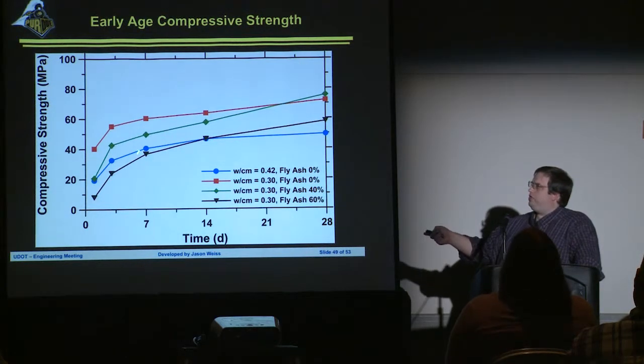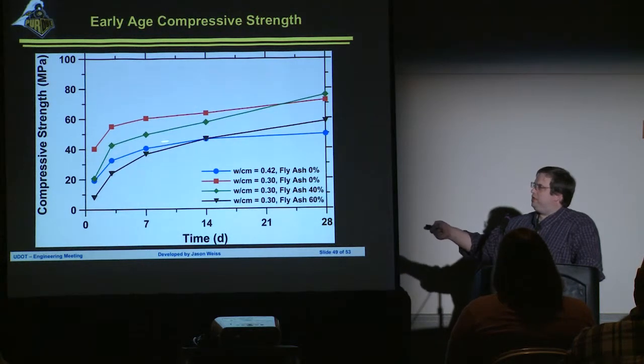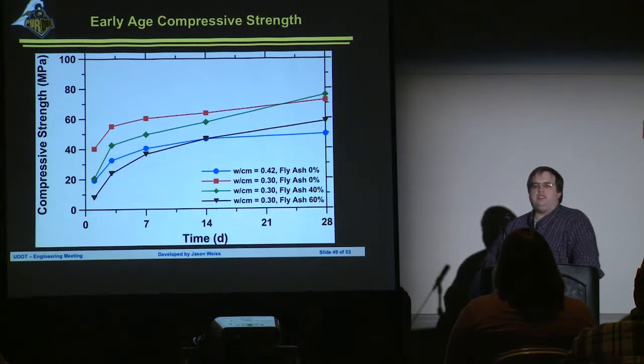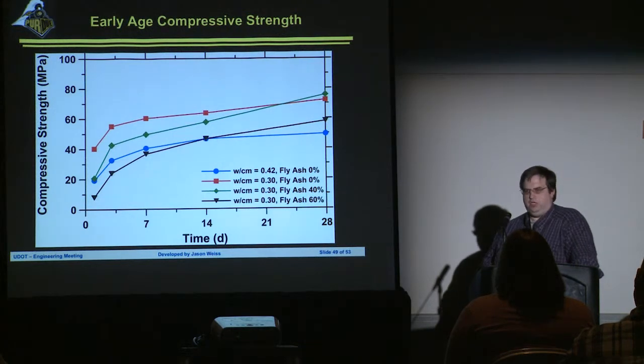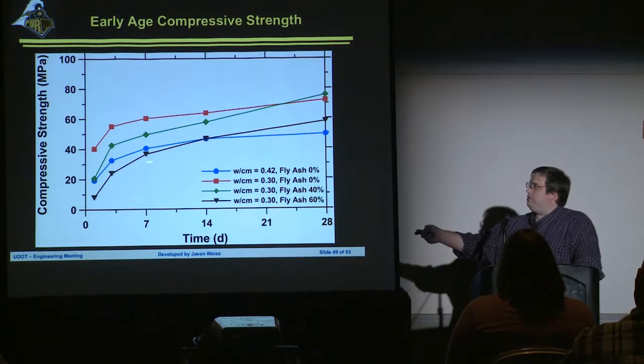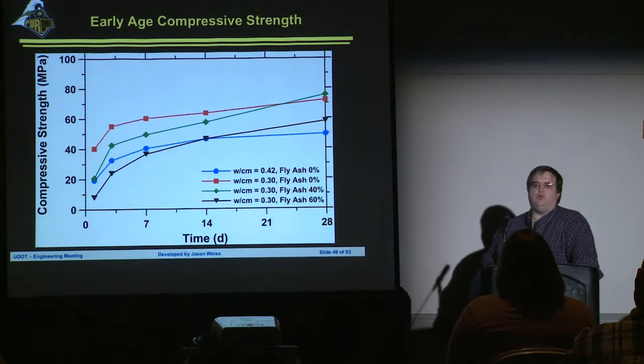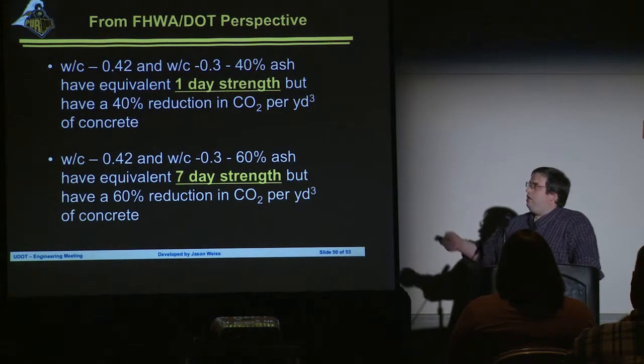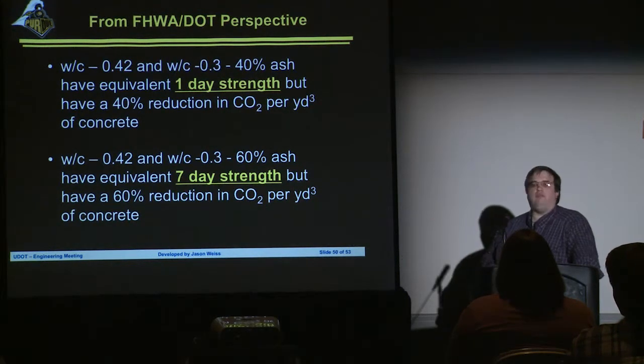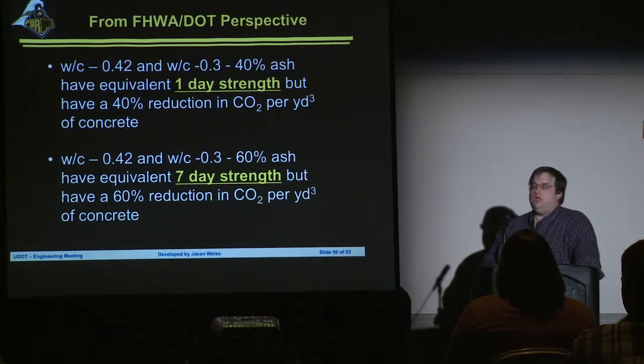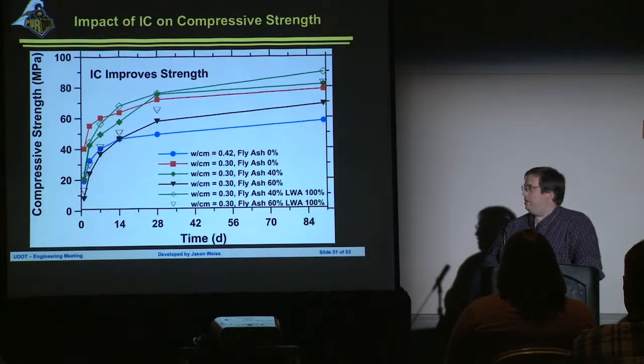But what we're really doing is we're saying we want to have our conventional mix, which is this blue line, and we want to take 60% of the clinker out of that concrete. So we're going to take 60% of our conventional cement out and we're going to replace it with fly ash. And what we've been able to see is at about 7 days we have almost equivalent strength. All right? And if we do it with 40%, we have an equivalent strength at 1 day. 40% less CO2. 60% less CO2 if we have equivalent 7-day strengths.